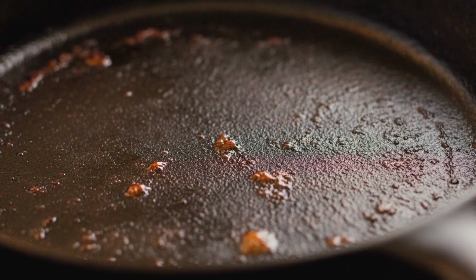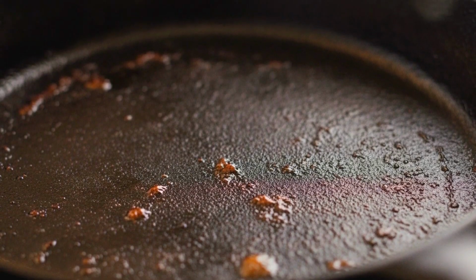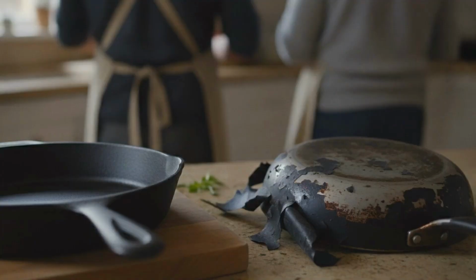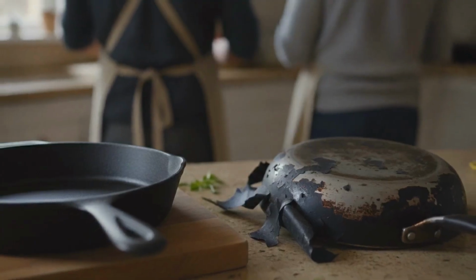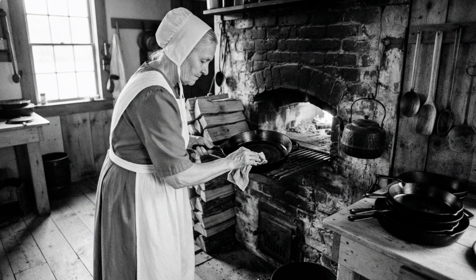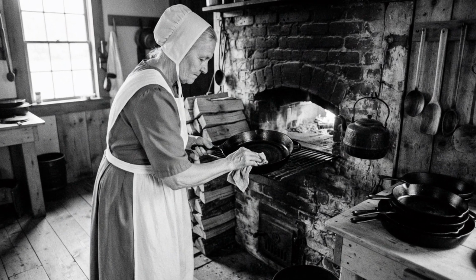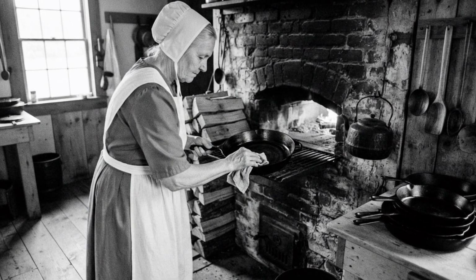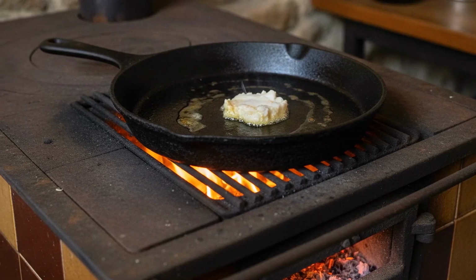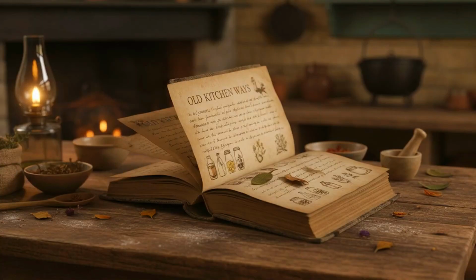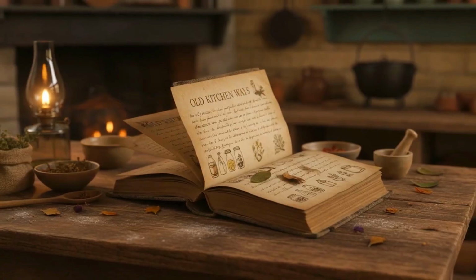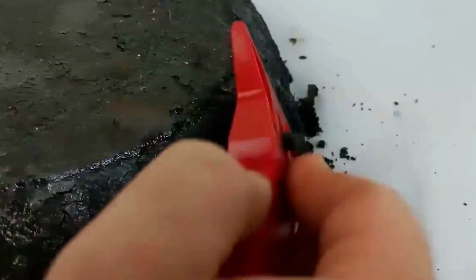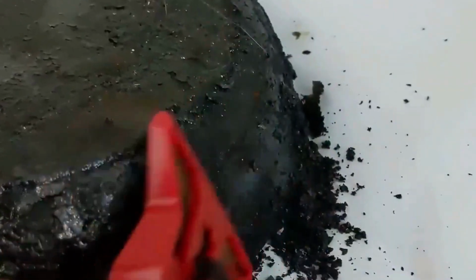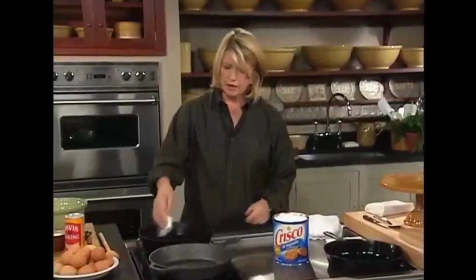Place the pan upside down on the center rack of the oven with a sheet of foil on the rack below to catch any drips. Bake for 1 hour, then turn the oven off and let the pan cool completely inside the closed oven before removing it. This single session builds one thin layer of seasoning. Repeat the entire process 6 times in succession before the pan's first use, and you will have a seasoning foundation that rivals a 100-year-old skillet.